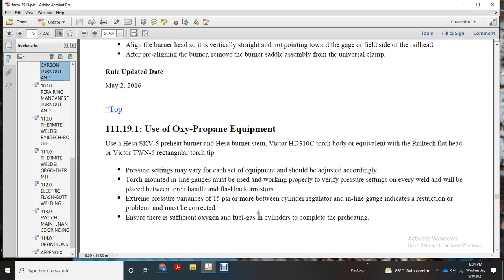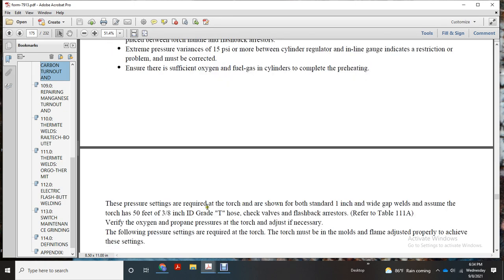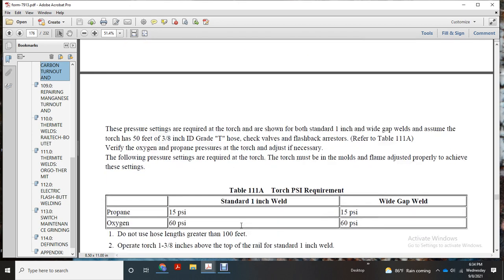Ensure there is sufficient oxygen and fuel gas in the cylinder for preheating. Pressure settings are required. The torch is shown with both standard 1-inch and wide gap welds. Assume the torch hose is 50 feet long, 3/8 inch inside diameter. Check the hose valve and flashback arrestors. Verify the oxygen and propane pressure for the torch. Adjust to achieve the following pressure settings required for the torch. The torch must be in the mold flame. Propane 15 psi, 1-inch wide gap 15 psi, oxygen 60 psi.